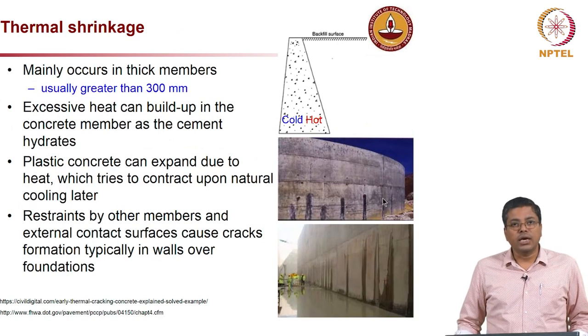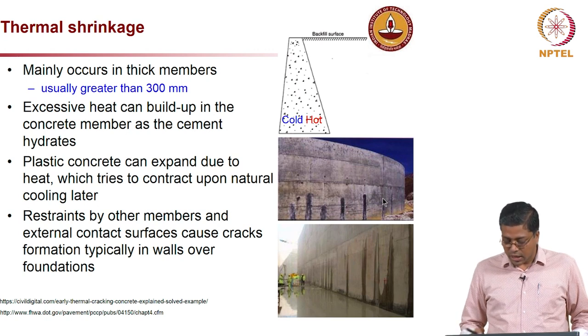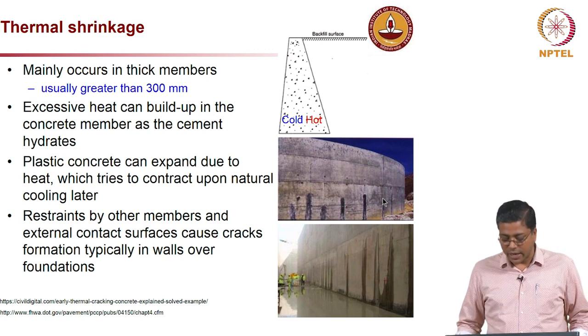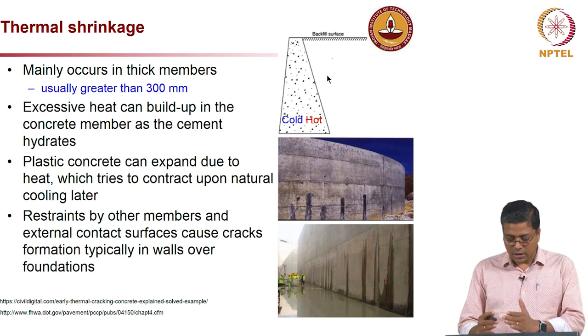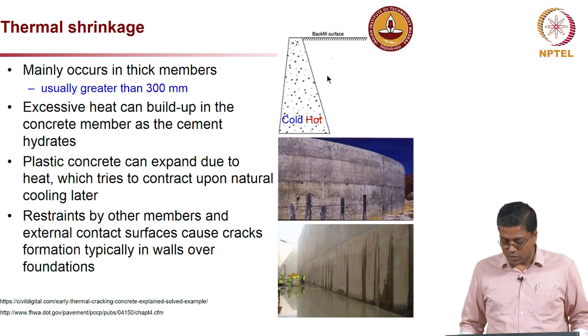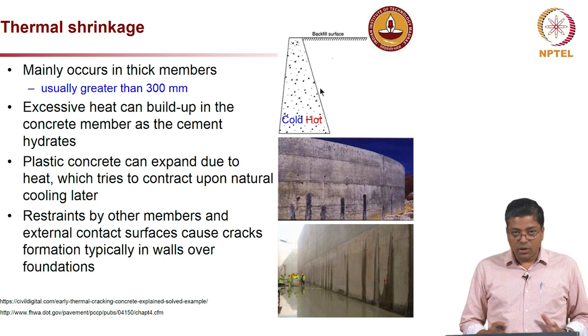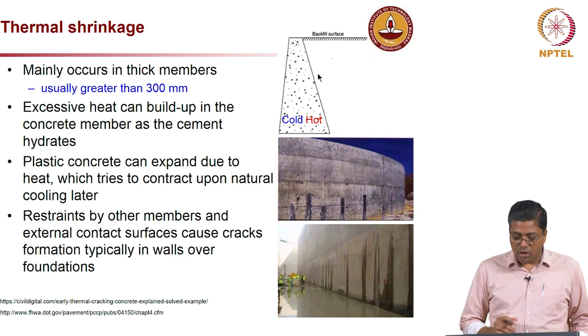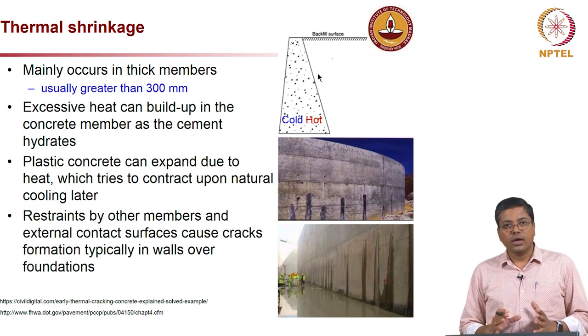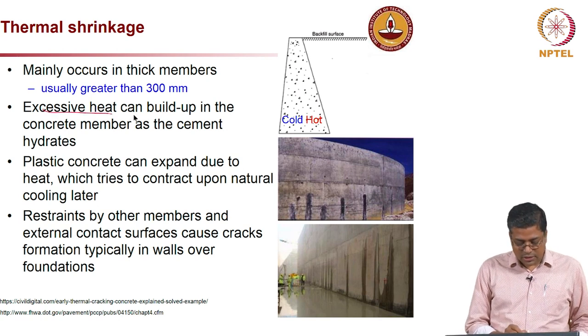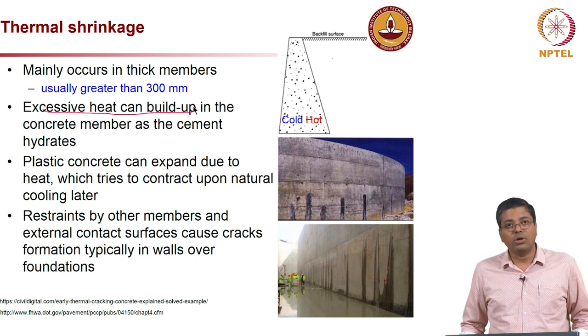Now thermal shrinkage happens mainly in thick members. As you see in the picture on the top right, I am showing a typical cross section of a retaining wall, where the thickness of the member increases as you go downward. When you have this thick section at the bottom, it is essentially mass concrete, and so there will be excessive heat generation especially at the bottom portions.